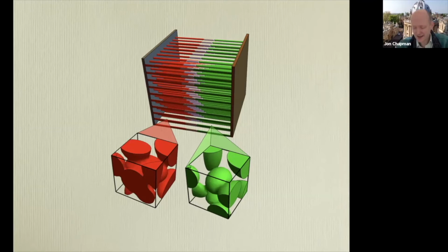It seems strange for a mathematician to say 2 plus 1 is not the same as 3, but in this case, you now don't have to worry about any lateral diffusion or connection between these one-dimensional models. They're only connected through the boundary conditions at the endpoints. That is simpler to solve than solving the full 3D problem. This is such a natural thing to do that often you do this without even realizing you're making this assumption, and that it is an assumption that you can effectively solve these as one-dimensional problems.